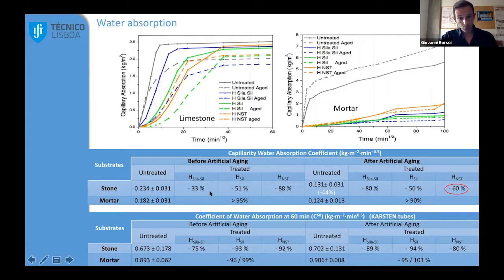On the other side, we can see that those two silane or siloxane products are quite linear. On the other side, there is an inverse trend after aging: after artificial aging, there is a reduction of the water capillary absorption in the case of the nanostructured product. Somehow the mortar is not much affected, because in both cases there is a high reduction of this water capillary coefficient, and this is reflected also in the Karsten tubes test. The same trend can be seen also on the limestone.